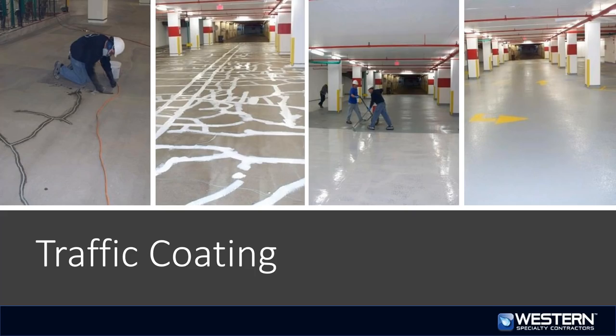And then the third picture actually shows the base coat material going down over the detailed cracks. And then once you put the base coat down and that cures, then you would put two top coats, or an intermediate and a top coat. Those are the coats that we then put the aggregate into. The aggregate is put in there to provide a more slip resistant surface, as well as to provide a wearing surface for the automobile traffic. So the picture on the right shows the completed project. We have the striper come in and paint the stripes. Usually it's striping to match what was there before, but this is a typical scenario for the traffic coatings that we put in parking garages.